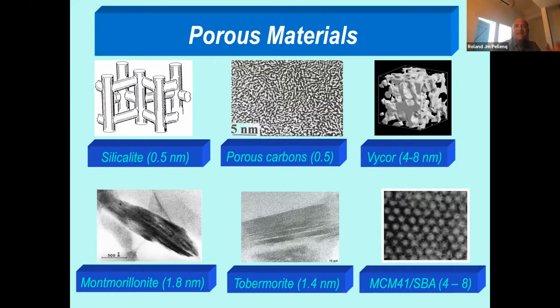So we are dealing with very tiny pores, what I call nanoporous, referred to in the literature as microporous. But don't get me wrong, most of you are mechanicians - microporous in this case means nano, not micron, okay? So microporous is less than 1 to 2 nanometers. It's actually for a very good reason.